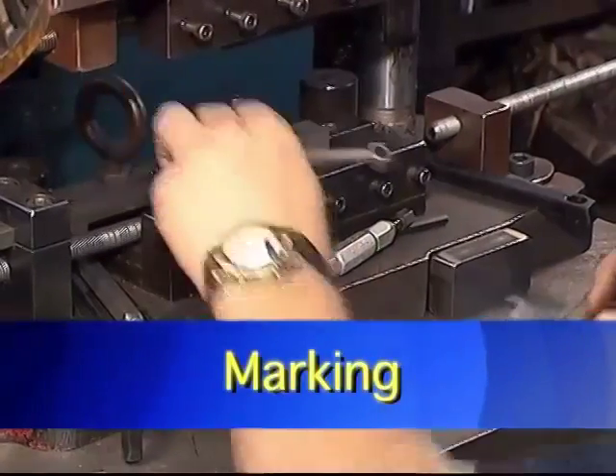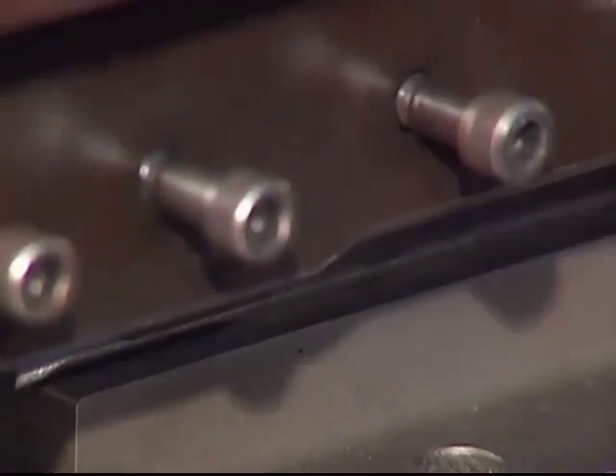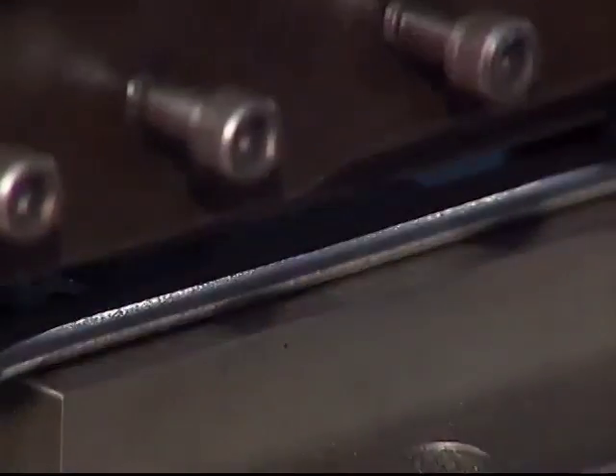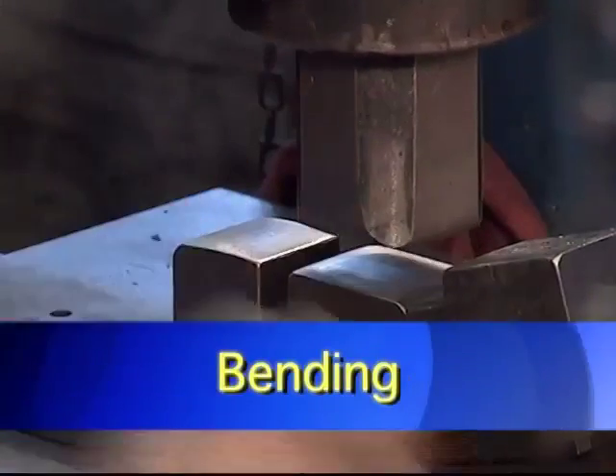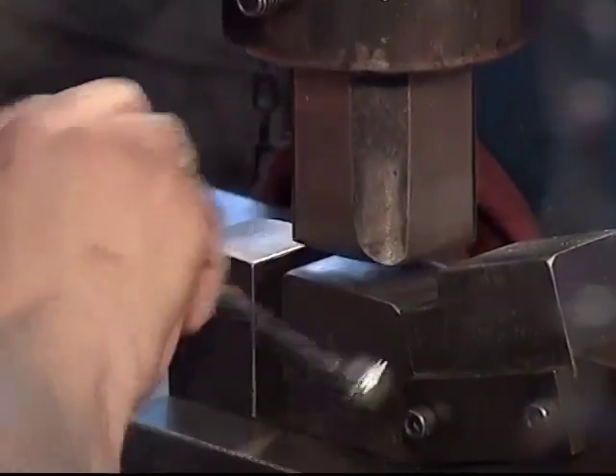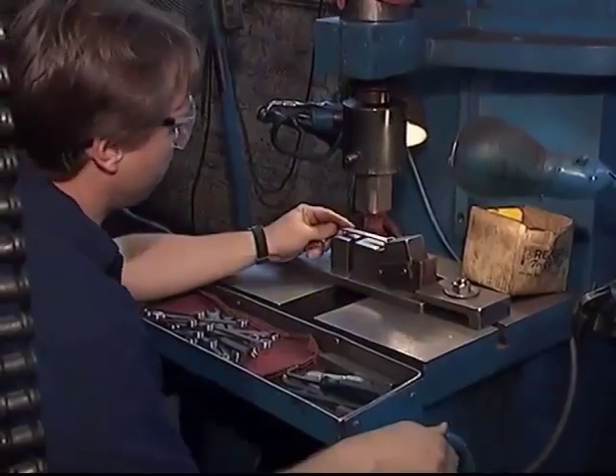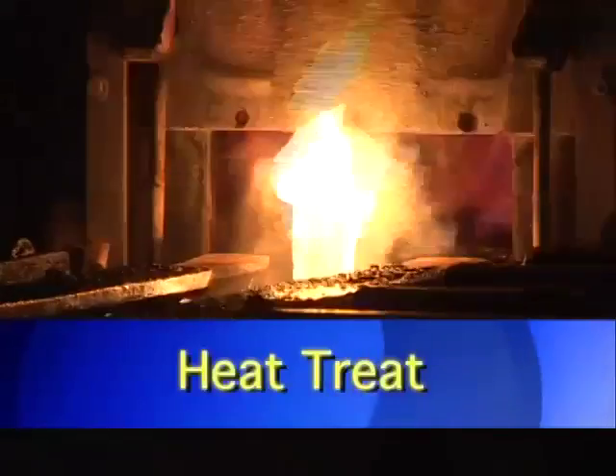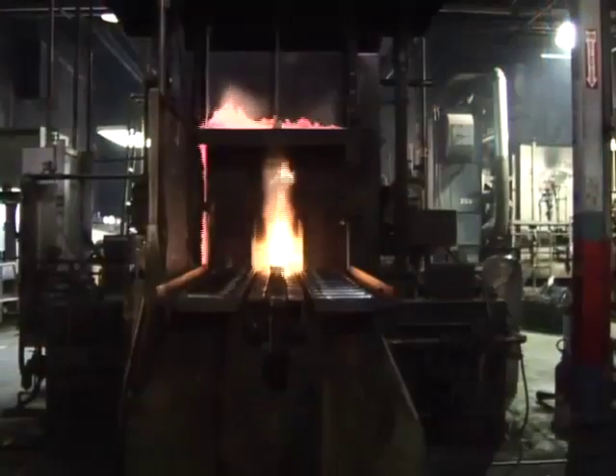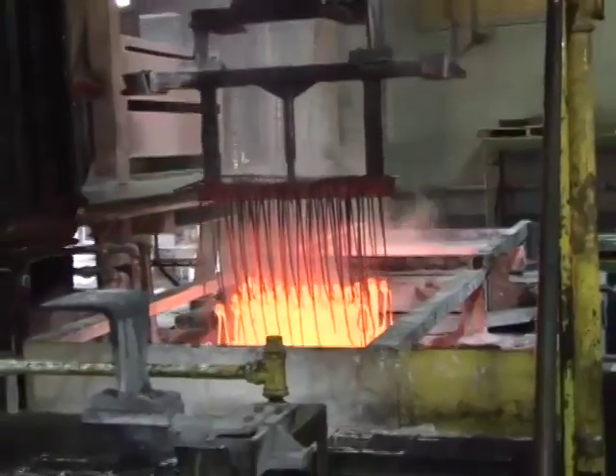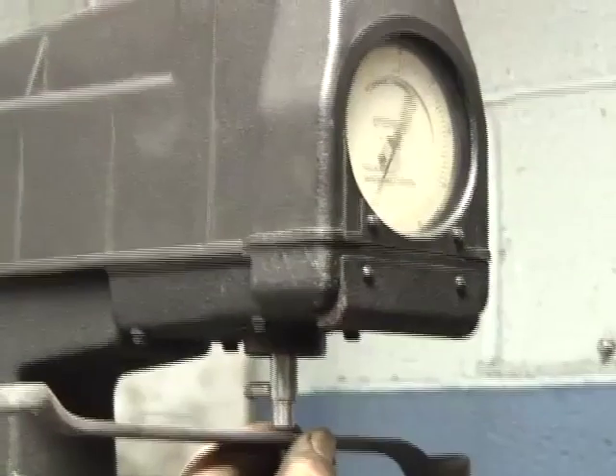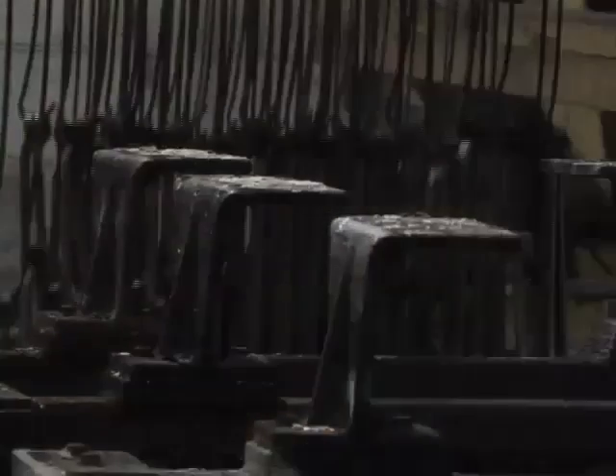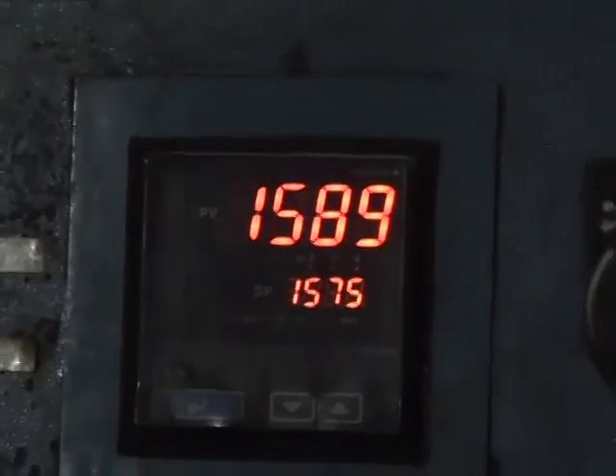Marking. Each wrench is then marked with the Cornwell name, the part number, and size. Bending. Some wrenches are bent if necessary to get the proper configuration and angle, such as found on a box end wrench. Heat treating. Cornwell uses 3 large furnaces. Wrenches are racked, heated, and dropped into quenching oil for 20 minutes. This will give a Rockwell hardness of about 56 to 58. Parts are then washed and placed in an endothermic gas-fired furnace, taken up to 1500 degrees and then tempered for 4 hours. This brings them within the proper hardness specification for strength and ductility.